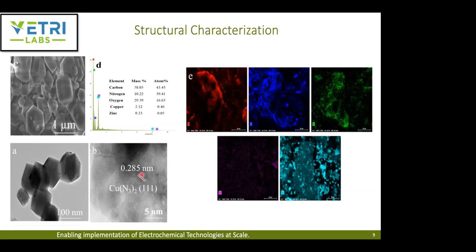And they also did this EDX analysis to confirm the weight percent and atomic percent of each element. You can see the atomic percent of copper is about 0.46. And you can see zinc is almost completely reduced because zinc gets evaporated at that high temperature, which makes nitrogen available, and then the copper gets doped and linked with the nitrogen present in the MOF.